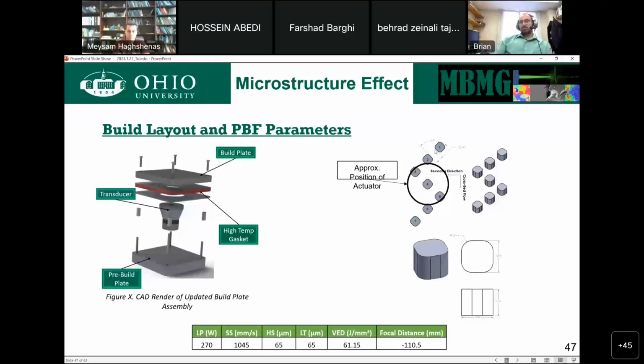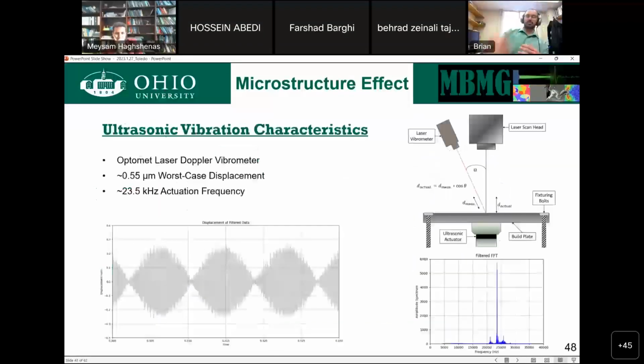We did some studies across different locations on the build plate, the circle representing the transducer. So we have samples directly on top of the transducer and those next to the transducer to understand if we're clamping this into a traditional system, how is that affecting the ultrasound at different locations? And we actually used the laser I told you before in order to see what kind of energy we were supplying. So in this case, we're applying about 0.55 micrometers at the center with a 23.5 kilohertz actuation frequency.